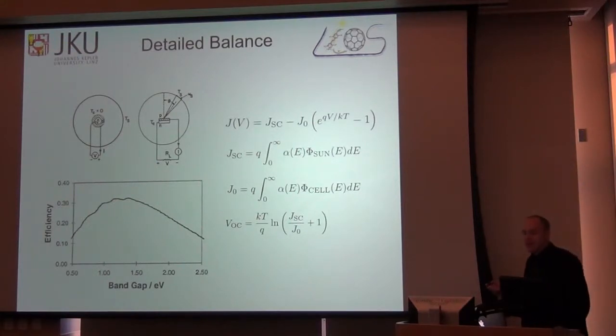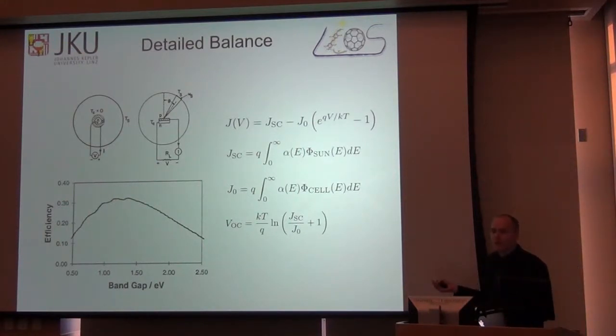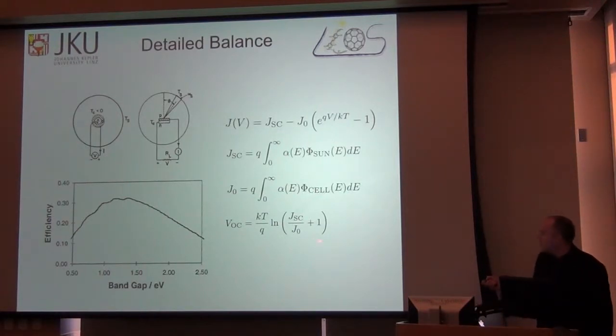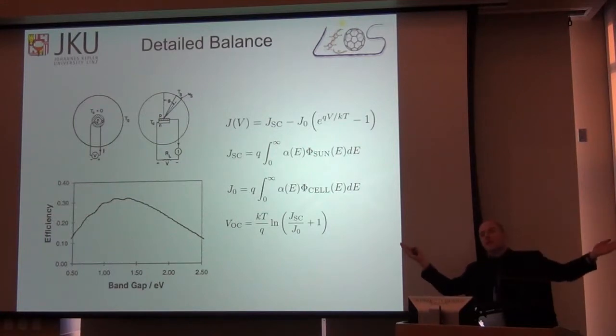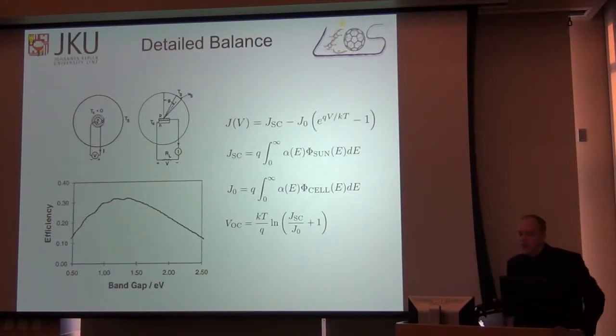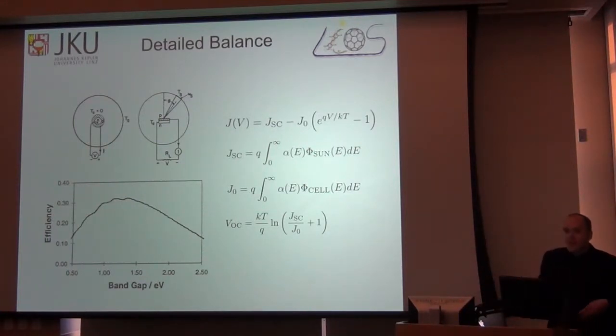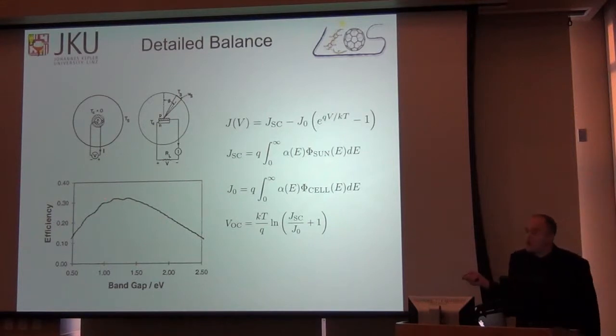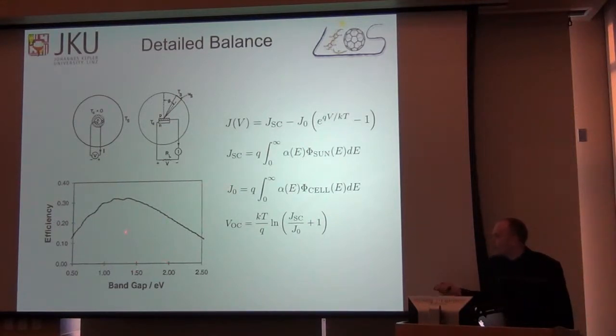And the way you can make your solar cell eventually reach that 44% limit is through concentration. So if your JSC becomes much, much higher than J0 through either concentration, which increases the intensity, or you can imagine it increases the solid angle that the solar cell sees the sun over. So at one sun intensity, if I just take a solar cell and put it on my roof, the maximum I can hope to get from a single semiconductor junction is 32%, not 44%. And that's at a band gap of roughly 1.3 eV.